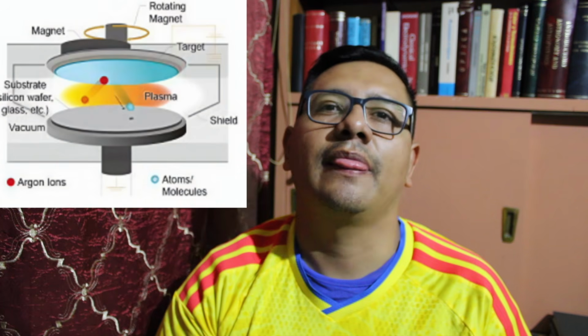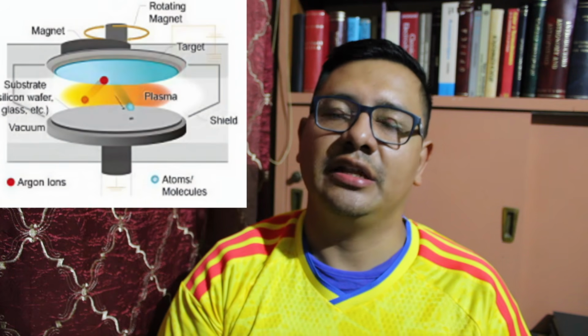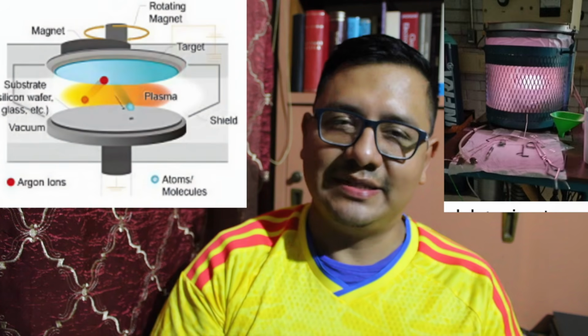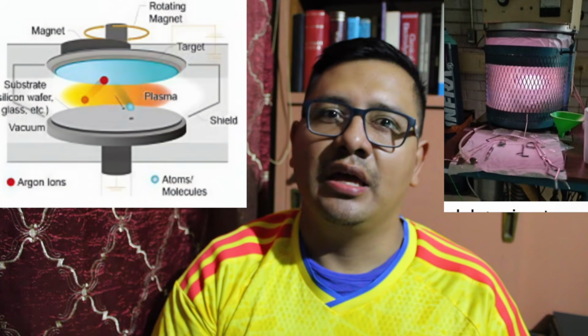Modifying this composition, first we tried with gallium nitride using argon as an inert gas to activate the plasma and to start the deposition, and then we changed it for aluminum nitride powder to create a solid target, and we also use argon as an inert gas to activate the plasma.